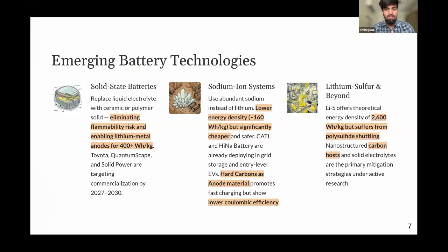The only drawback with sodium ion is it has a lower energy density as compared to lithium ion, and this is because of the electropositivity of sodium. It is not a dominant chemistry as compared to lithium, but we can use it for specific applications like grid storage at entry level, and we can innovate on the energy density until it can be used for automotive and EV mobility applications also. It uses cathodes of sodium vanadium phosphate, sodium iron phosphate,